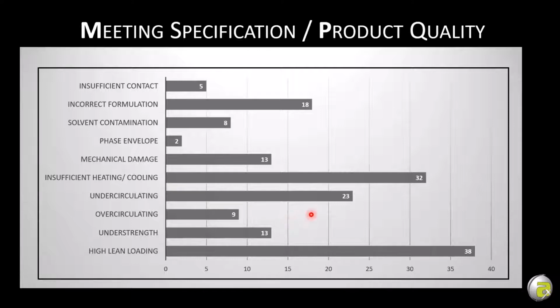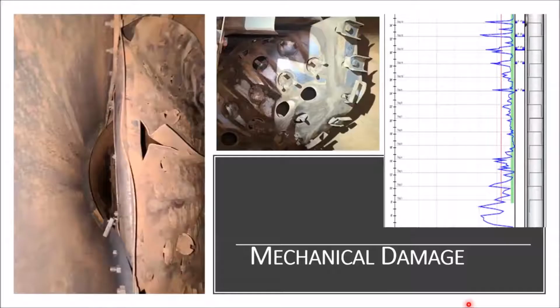Over circulating can actually be a problem. Many people, when they go off spec, the first thing they do is crank up the pump. I need more amine in the tower. But the problem with that is, as you increase your circulation rate, it increases the duty load on the reboiler. And if you don't account for it, you suddenly don't regenerate the solvent as well. So by over circulating, you end up in this high lean loading problem. Also sometimes the coolers don't work as efficiently when the amine is pumping through rapidly. And under strength: you need to have a certain quantity of amine in your circulating solution to account for how much H2S and CO2 is coming in with the feed.